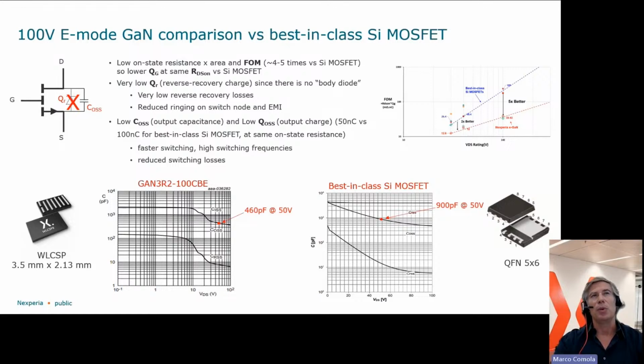So you have also low on-state resistance per area and the figure of merit that, if you compare, you can see on the right side in the diagram versus the silicon. The silicon has 4 or 5 times higher at the same voltage, at the same 100 volt. So if you reduce the figure of merit, of course, it means, in other words, that at the same on-state resistance, you have 4 or 5 times lower gate charge.